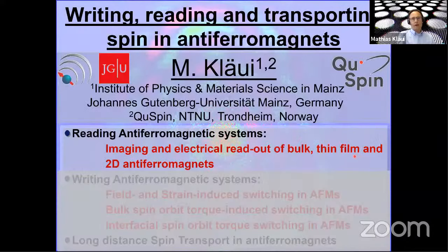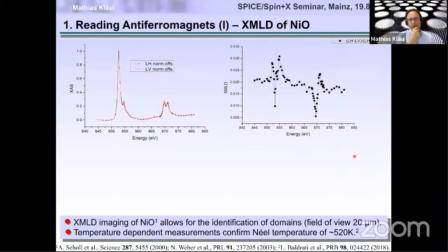And I'll show you how we can image and electrically read out thin film, bulk, and 2D antiferromagnets. So one of the best well-known approaches to read out antiferromagnets is X-ray magnetic linear dichroism. This is a very well-established technique. And this X-ray magnetic linear dichroism means that if you go to an absorption edge of, for instance, nickel in nickel oxide, then you get a linear dichroism, meaning that the absorption of linearly polarized light of that energy along this direction and this direction is different, parallel and perpendicular to the Néel vector.